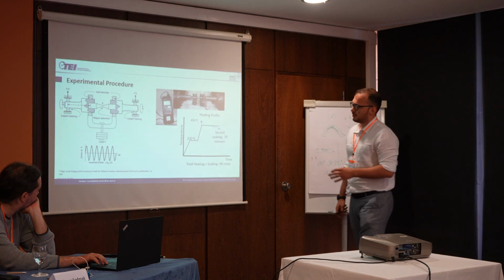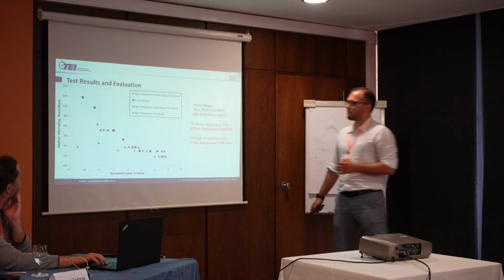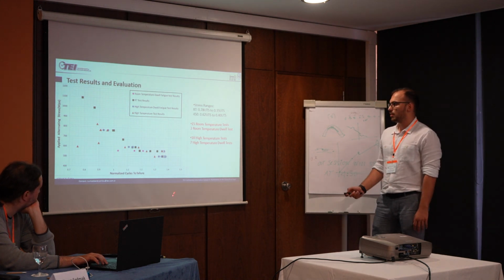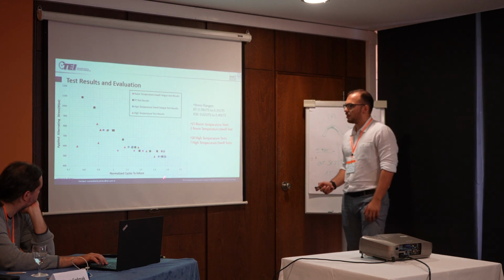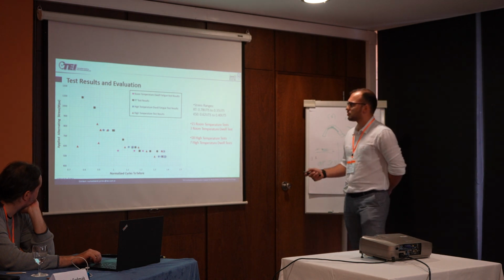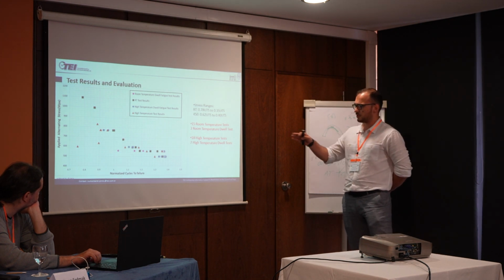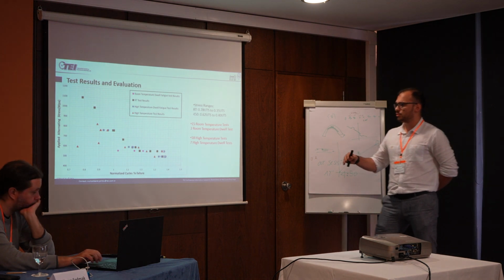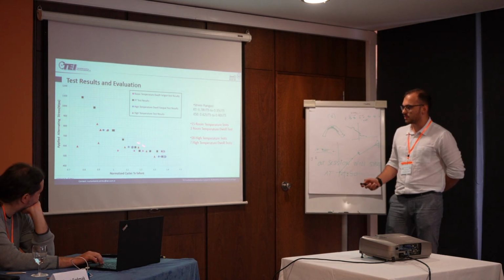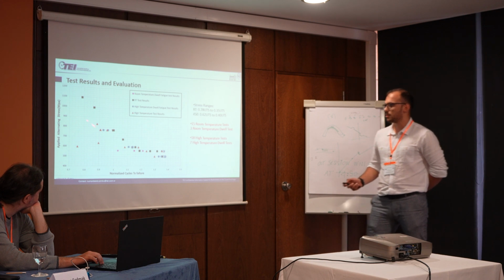Total soaking time and heating time is about 90 minutes for each specimen. We can continue. Here you can see the raw data from our tests. We have coupled runout data here, and we performed our tests at approximately 70% UTS to 35% UTS for the specimens at room temperature, and about 60% UTS to 40% UTS at high temperatures. We can see that there is a little scattering here, but the higher stress values look fine. We can continue.